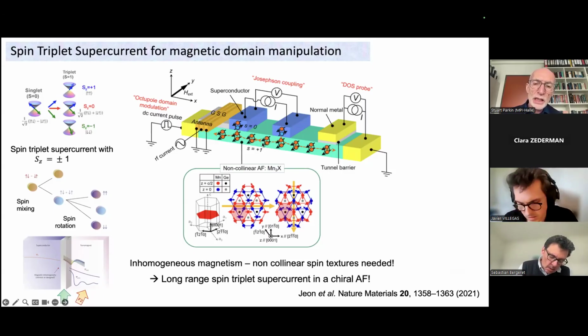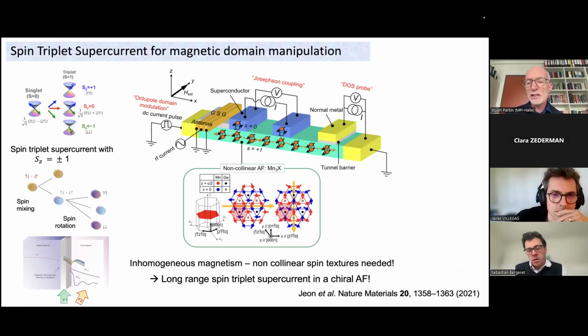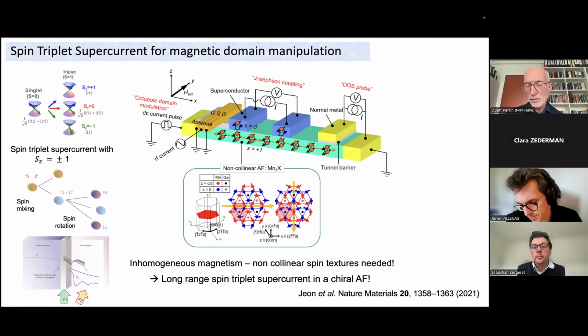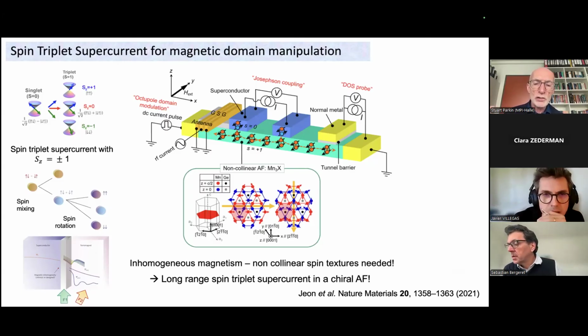through the non-collinear antiferromagnet. So you would expect that these very large manganese moments would destroy the Cooper pairs, but they don't. Rather, they allow the propagation of long-range supercurrents over very long distances, and we showed more than 150 nanometers, which is a long distance. And so we argued that this was the first evidence for an atomic non-collinear antiferromagnetic structure where supercurrents could flow over long distances.